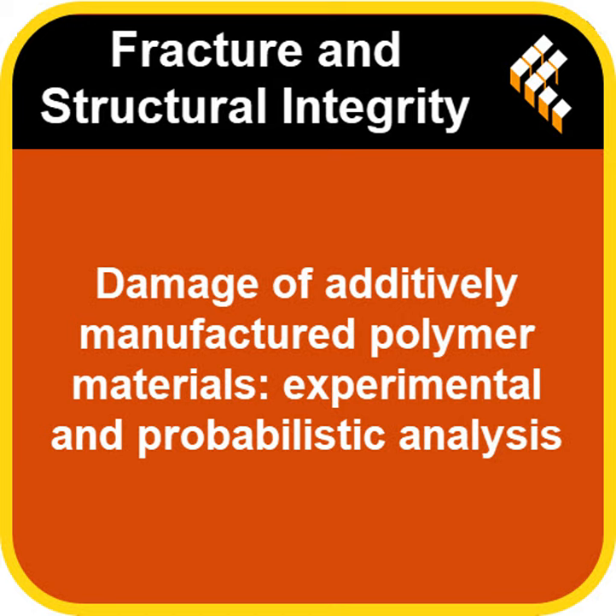Definitely. And they also broke down the material's response under stress into 3 distinct zones. This shows how its behavior changes as the load increases, and importantly, how those zones shift depending on the orientation. Okay, what are the zones? Right. Zone I is the elastic zone. Basic mechanics here: if you release the stress, the material springs back to its original shape. It's temporary, reversible deformation, like stretching a rubber band just a little. Exactly. The stress range for this varies by orientation, like maybe 0 to 35 megapascals for the weak 90-degree orientation in their tests. Okay, then zone 2.